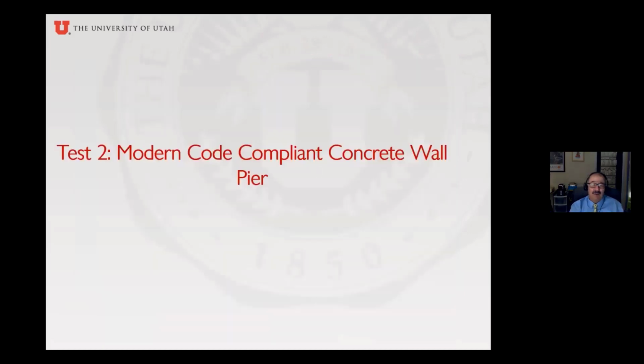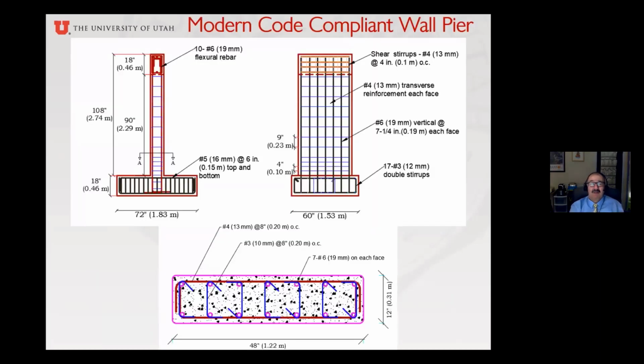Now, the modern code compliant concrete wall pier, how good is it? Or how bad are the existing wall piers? So for this one, we built it according to the AASHTO LRFD code. We made sure we didn't have any splices here at the bottom of the wall. All the dimensions were identical for the footing, for the wall, but the cross-section, as you can see in the reinforcement, is meeting the code, meaning we have more than 1% steel ratio. We have good seismic hooks, you see, as the code requires now.